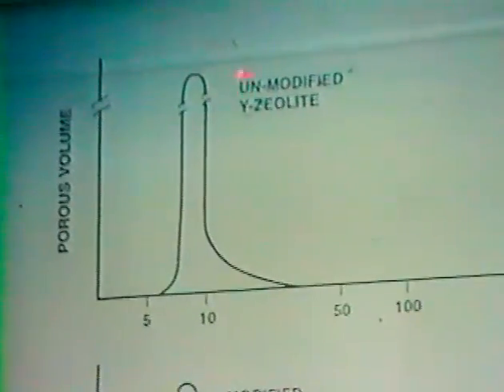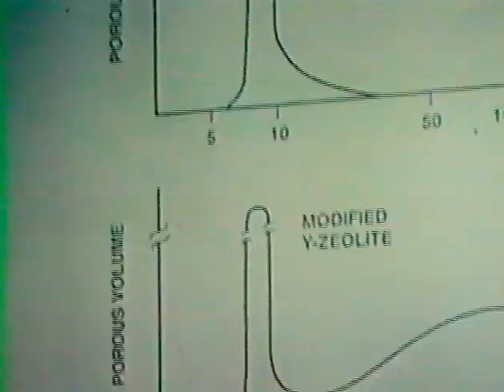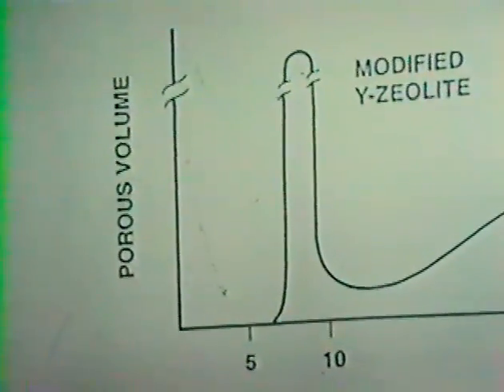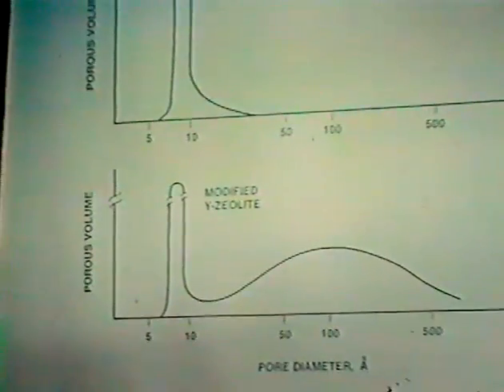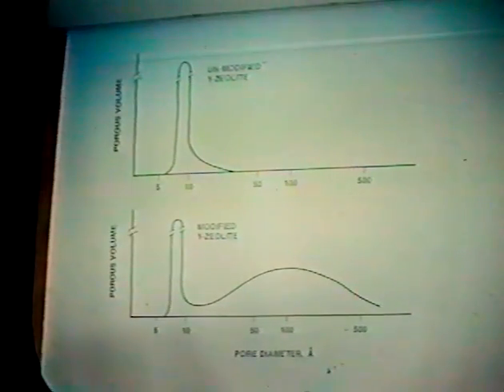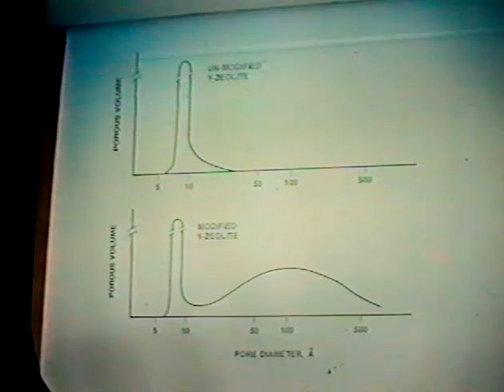One of the most dramatic changes is a big change in the pore distribution. Zeolites are often regarded as having a uniform pore distribution around about 8 angstroms, and this is completely true for as-received sodium Y or various other materials. As soon as one treats these in a hydrothermal atmosphere, one removes aluminum ions from the structure and produces a mesopore region, usually centered around about 100 angstroms. The more one steams the zeolite, the more this volume of pores and the enlarged pore diameter increase.